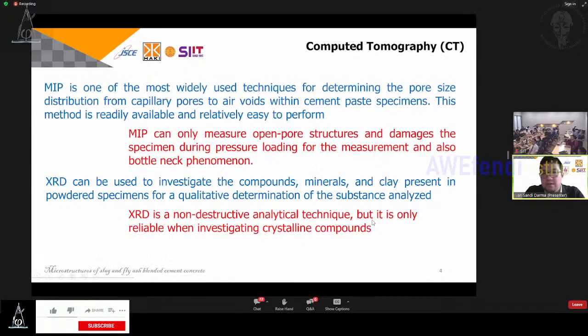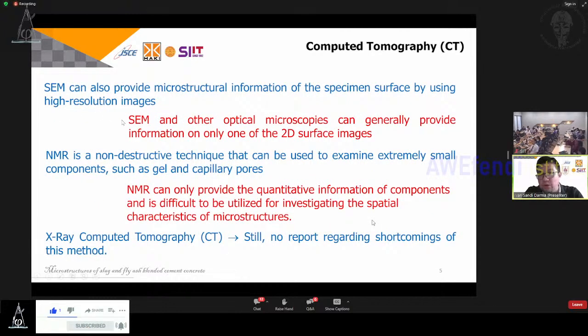MIP is one of the most widely used techniques for determining pore size, but the drawbacks, as we know, are the bottleneck effect and damage to the specimen during pressure loading. XRD is a non-destructive analytic technique, but it is only reliable when investigating crystalline compounds. For SEM, we know it is only two dimensional. NMR is quite difficult for investigating spatial characteristics. But for X-ray, up to now, there is still no report regarding shortcomings of this method.